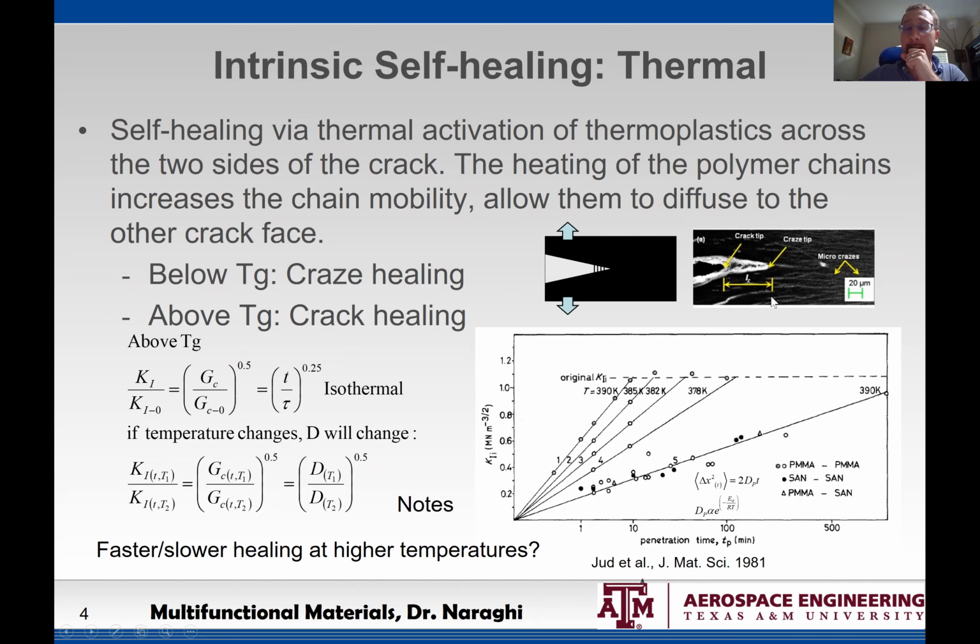Now, one thing that becomes very important in healing of thermoplastics is the concept of craze versus crack. If I'm advancing the crack tip, inside this region you have polymer chains that still have one leg on one side and the other leg on the other side, and the crack tip has not opened enough for these chains to let go.